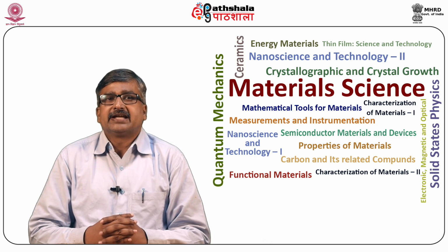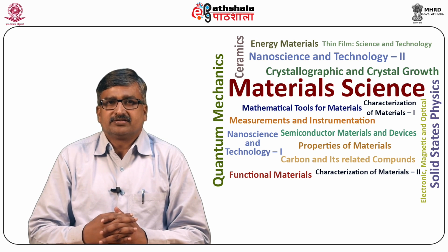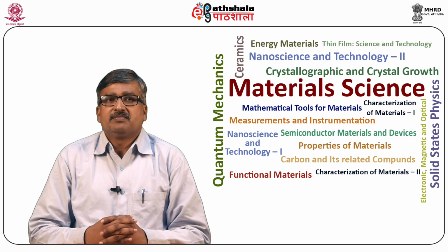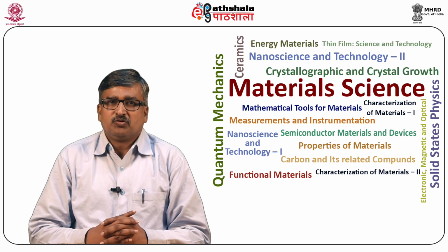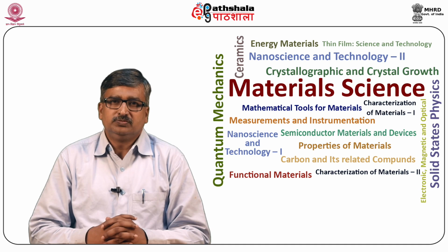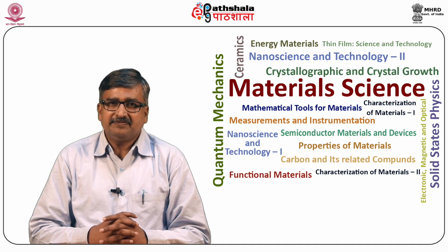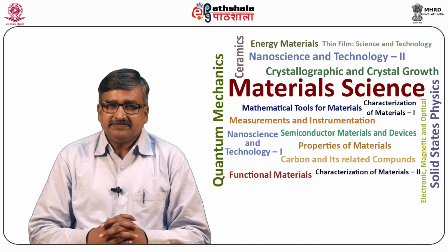Let us discuss the gas phase purification. This is the technique which was developed by Ebbesen and co-workers. In this process, they heat the carbon nanotubes in the presence of oxygen at a very fixed temperature so that the vitreous carbon or amorphous carbon evaporates first, leaving behind the carbon nanotubes.